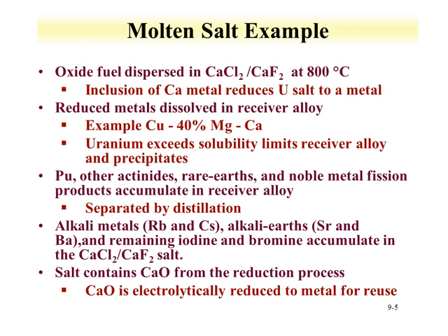Once reduced, the uranium metal can be removed from the salt phase by being dissolved into a second phase called the receiver alloy. For example, an alloy of copper, magnesium, calcium can be produced. The uranium is dissolved into this phase. It exceeds the solubility limit in the receiver alloy and precipitates. So you have separation of the uranium as it goes from the oxide phase at the initial component, is reduced to the metallic phase, goes into this receiver alloy and precipitates out.